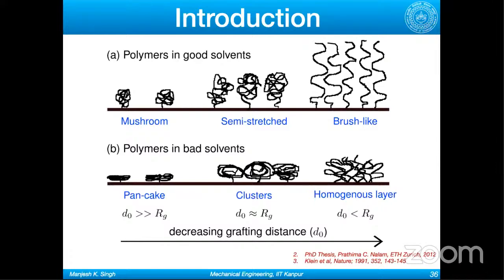So if you have polymers in a good solvent and you attach or graft one end in such a way that the distance between two neighboring chains or grafting sites is much higher than the radius of gyration of the individual chain, they'll form a mushroom-like structure. If you move them closer and the distance between the grafting sites is of the order of the radius of gyration of the chain, they will be like semi-stretched. If you bring them even closer, so that the distance between two neighboring sites is much lower than the radius of gyration of the chain, they'll stretch out to form a brush-like structure because of entropic and excluded volume effects, which we call a polymer brush normally.